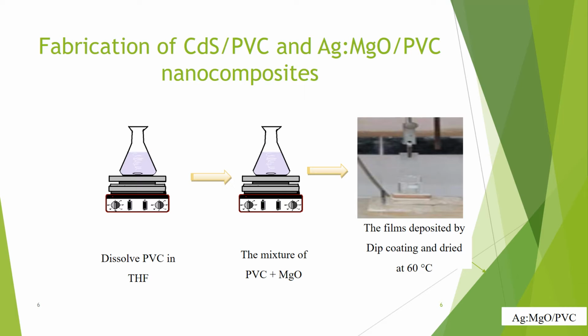This diagram summarizes the process for preparation of magnesium oxide PVC nanocomposite. First, we dissolve PVC powder in THF for 30 minutes under stirring to obtain a viscous transparent solution. Then we take a weighed amount of magnesium oxide nanoparticles in THF. After that, the two solutions are mixed for 1 hour. The dip coating technique was used to deposit the magnesium oxide PVC nanocomposite on glass substrates.